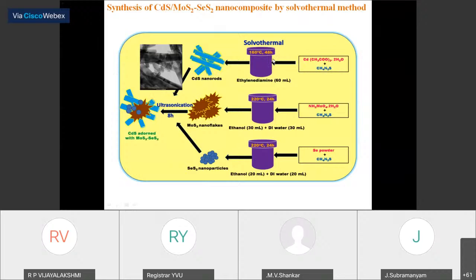So in this one, we synthesize the cadmium sulfide nanorods by using the solvothermal method, and the reaction process is the same as that of the chemical precipitation method, but we have used the autoclave, and by using the autoclave we obtain the cadmium sulfide nanorod. Then we have the molybdenum disulfide. We synthesize the nano flakes of the molybdenum disulfide also by using the hydrothermal method.